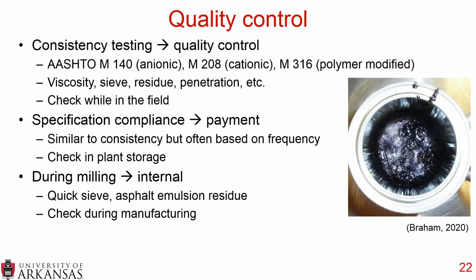And then during milling and internal type testing, you can do a quick sieve. This is literally running the asphalt emulsion over a window screen just to see if any large balls of asphalt binder exist. And then you can also run asphalt emulsion residue tests, which is that picture on the right. And that's just a boil off to make sure you have the proper amount of asphalt binder in your asphalt emulsion. And these are things you can check during manufacturing.